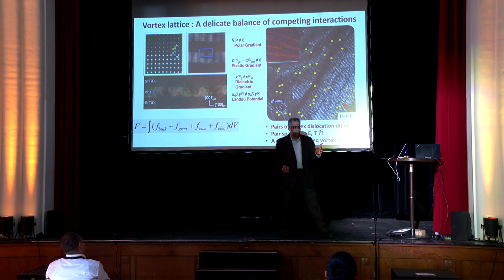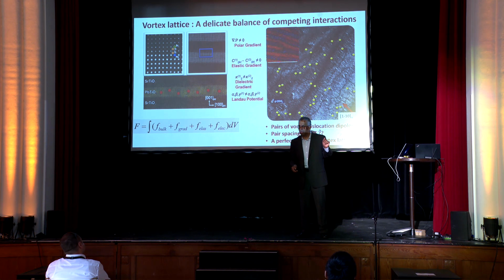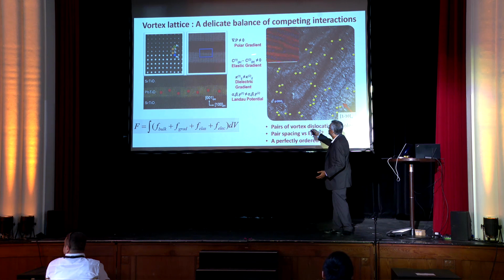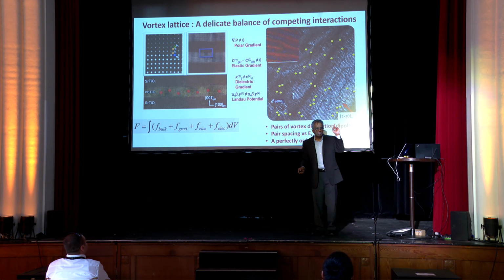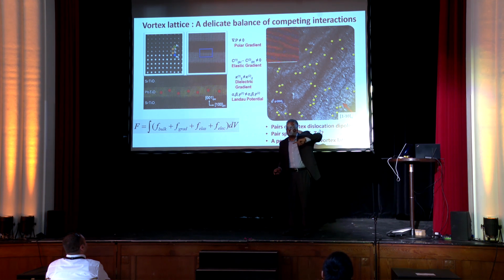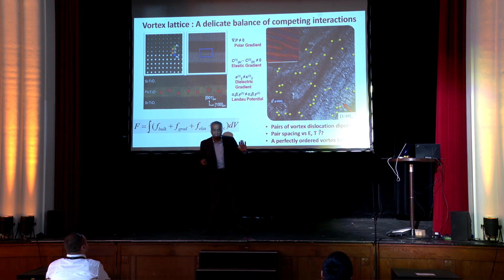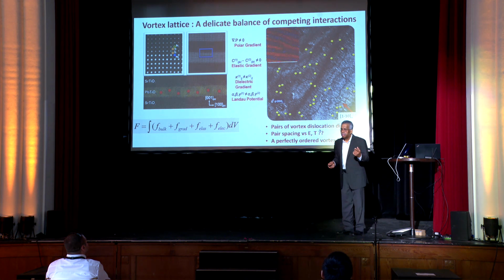Now, in a case of a ferroelectric, which is not true in most ferromagnets, except maybe in rare earth ferromagnets and stuff, in a ferroelectric, the spontaneous dipole is coupled to the lattice. So people will tell you that barium titanate is tetragonal, bismuth ferrite is rhombohedral. So if you impose boundary conditions like you do here in the polar gradient, then the system is saying, I have a very large polarization, I might as well put it in plane. Okay? And so if I impose this kind of a boundary condition, the implicit answer is put the polarization vector in plane. But it can't do that because it's stuck to a substrate. And therefore, when you start to stretch the lattice, it says, I can't do that because this term begins to dominate. So if you have the elastic and the electrostatic terms of approximately the same, meaning you have competition between them, you start to get these emergent textures.